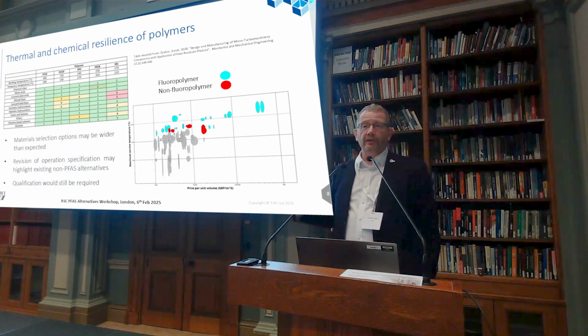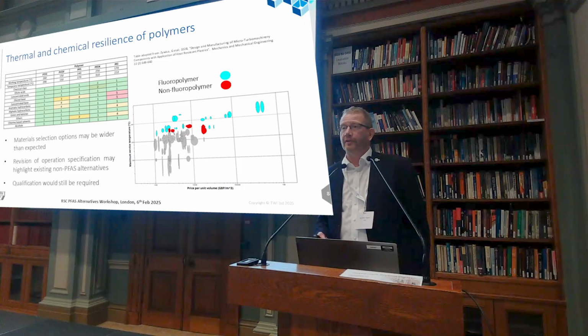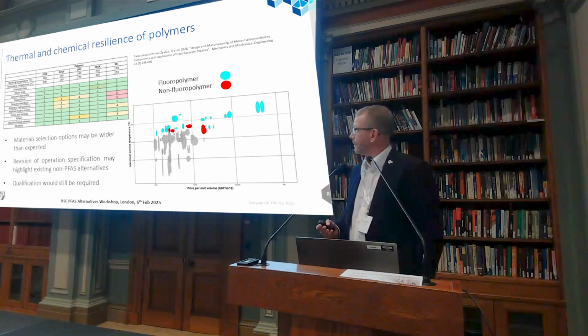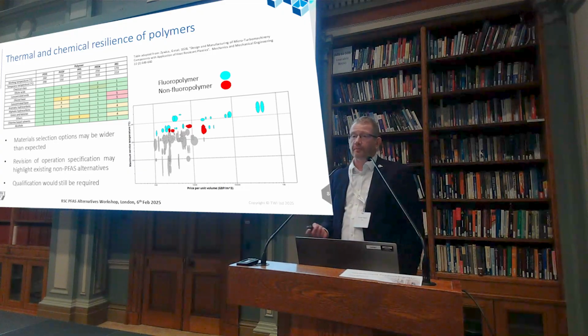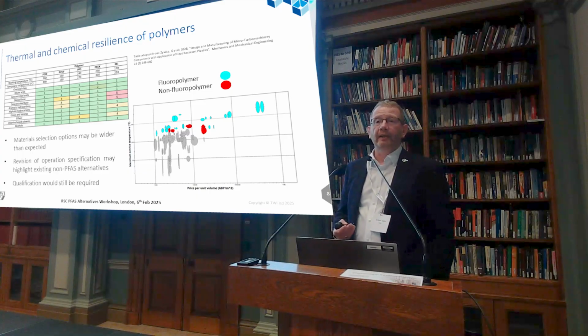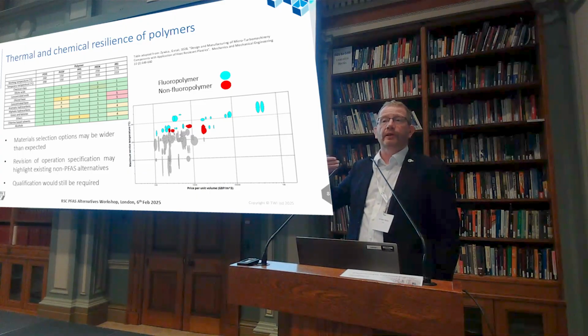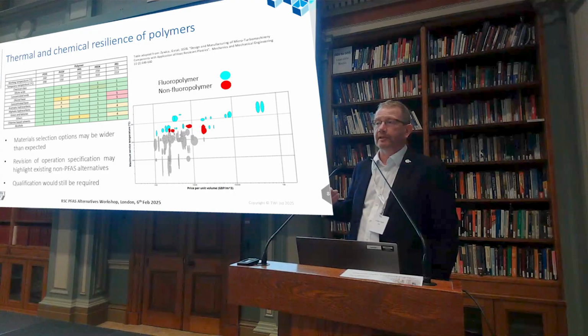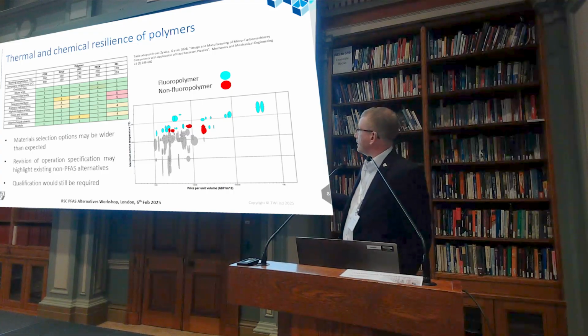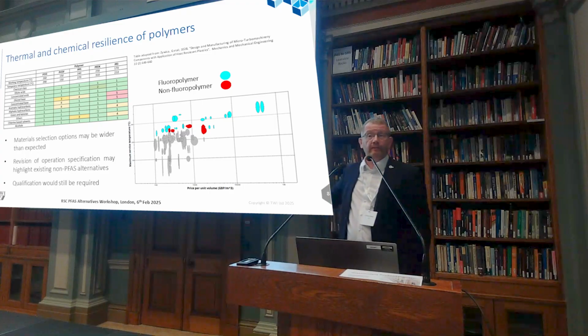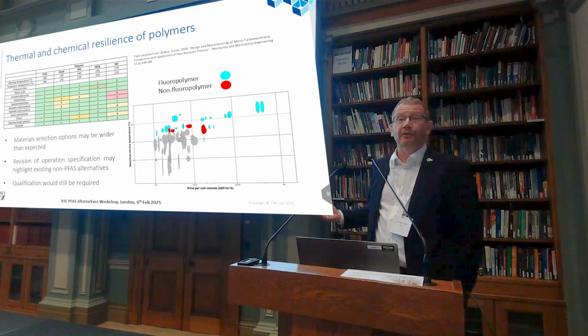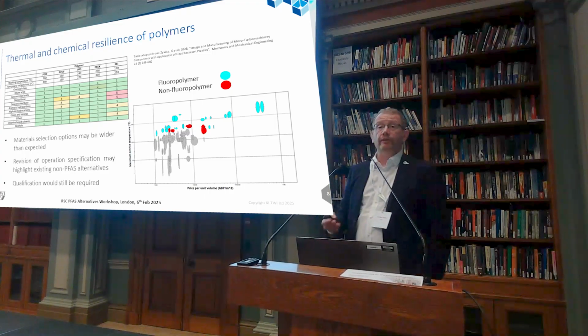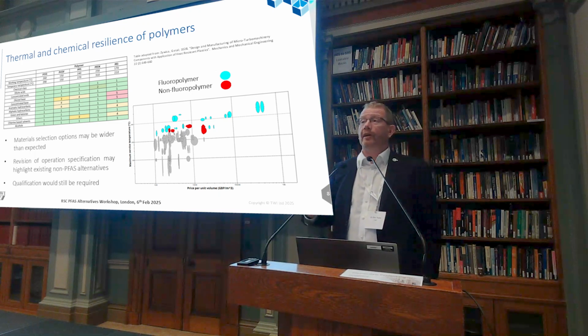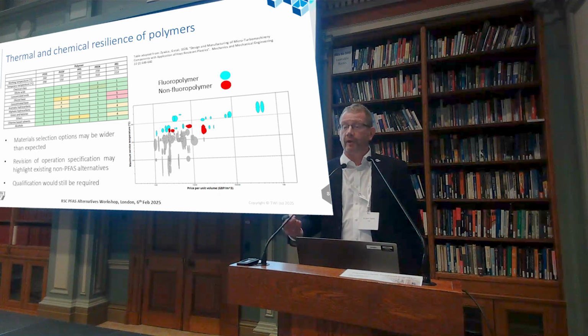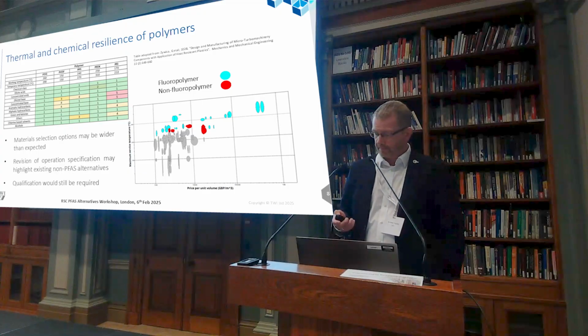So the table on the top left is similar to some of the tables that Richard was showing on the right-hand side. So these are Ashby plots, and what I've put in here are some very simple terms, and we're looking at operational capability of 170 degrees plus. Well, fluoropolymers dominate. Some of them are also really quite expensive, so that might be a pressure to look at alternatives. The ones in red are non-fluoropolymer-based materials, and they are primarily, not exclusively, but primarily siloxane-based.